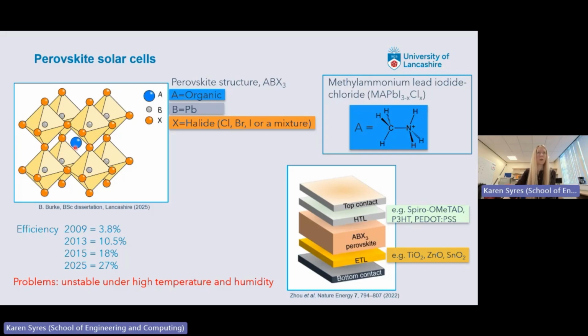A is the atom in the middle, which is some organic molecule. B is usually lead, although lead is toxic, so there are some efforts to remove lead and replace it with something that's not toxic. And X, the orange ones, are halides, so something like chlorine, bromine or iodine, or you can have a mixture. The one that we were looking at was called methyl ammonium lead iodide chloride. The organic bit is this molecule here, where you've got this CN bond, and then we had a mixture of iodine and chlorine in there.